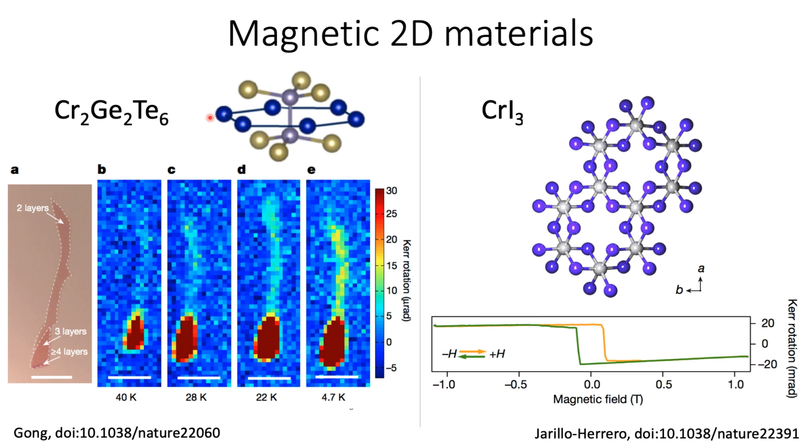My experiment had two issues. In particular, my ferromagnetic resonance measurements had two issues. The first was that the resonance of the chromium germanium telluride was a little bit outside the range of my equipment. And also, chromium germanium telluride was a little bit chemically unstable. Now, at the time, I knew that Pablo Jarillo-Herrero at MIT was working on chromium triiodide, and we discussed a bit the chemical stability of chromium triiodide, and it turned out that it was worse than that of chromium germanium telluride. So I was a bit stuck.